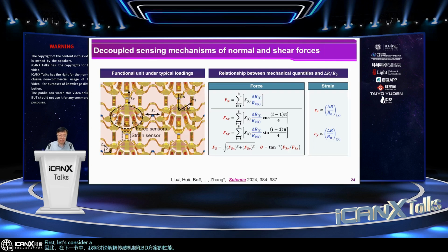First, let's consider a functional unit subject to a combined normal force and shear force loading. Here, according to the static equilibrium analysis, we can correlate the normal force and two shear force components explicitly with the relative resistance changes of the 8 force sensors. If you look closely into these equations, you will find that the normal force is actually proportional to the average outputs of the 8 force sensors, but the shear force component is proportional to the difference of 4 sensors relative to the other 4 sensors.